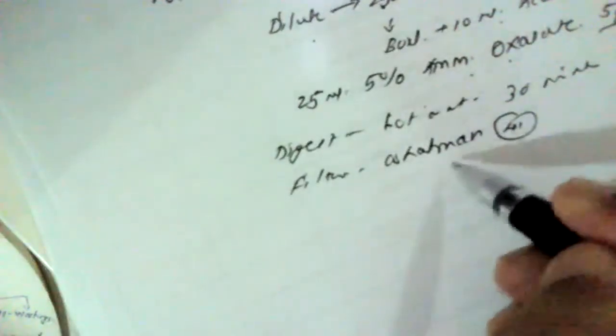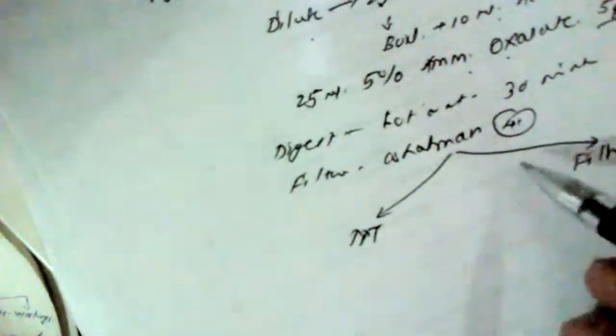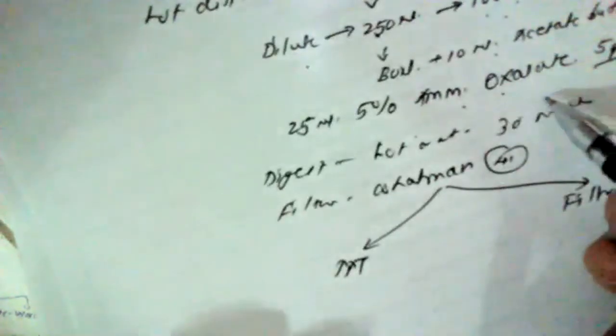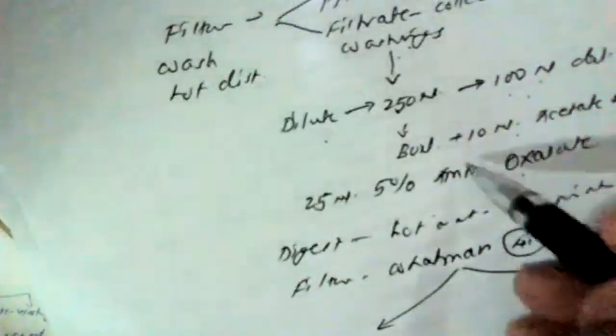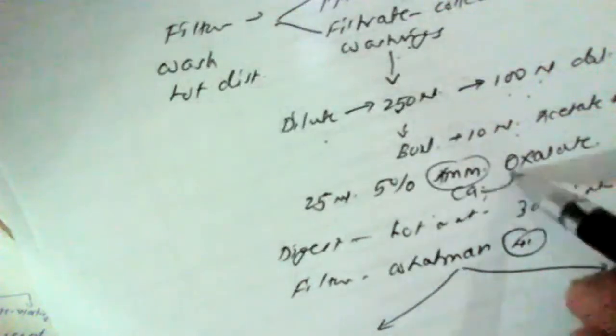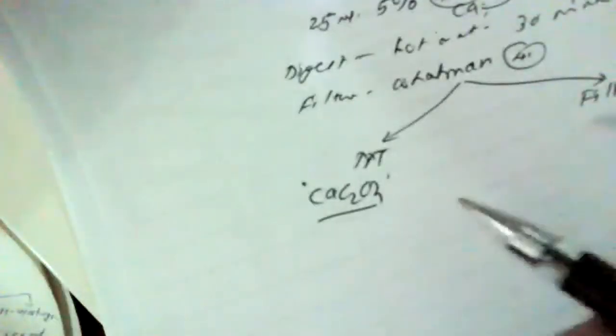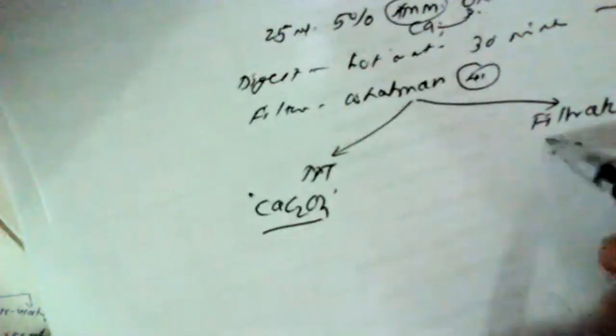After this, we have to filter the content by using Whatman filter paper number 41. So after filtration, we have again two parts: a precipitate and a filtrate. By adding this 5% solution of ammonium oxalate to this solution, whatever calcium is there is converted into calcium oxalate. The ammonium ion is replaced by calcium, which turns to be calcium oxalate, a white colored precipitate. So this is how we have separated calcium, and the filtrate contains magnesium.